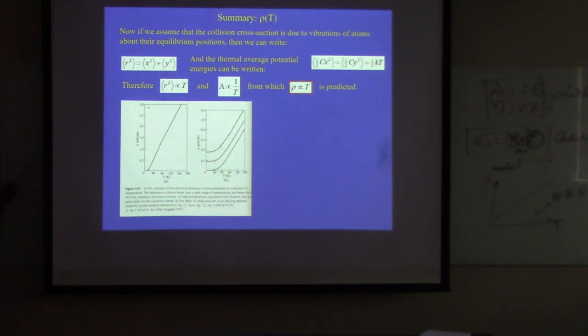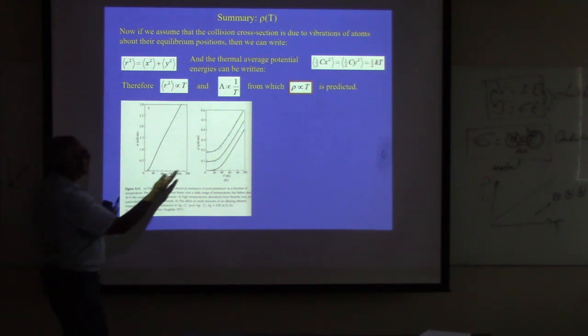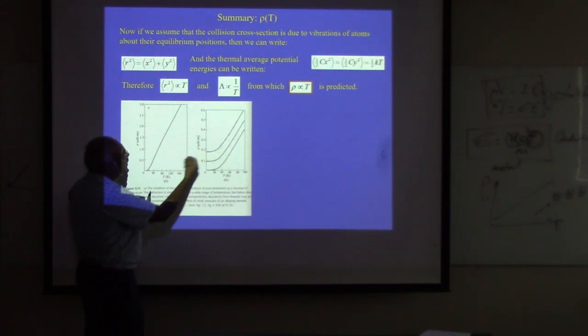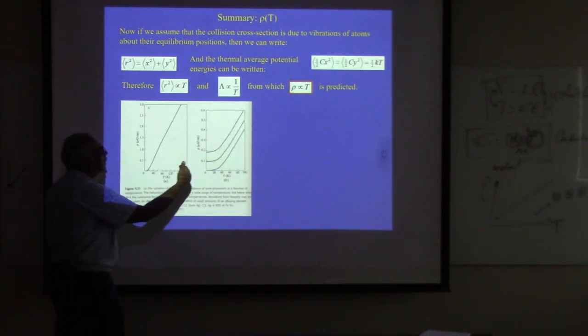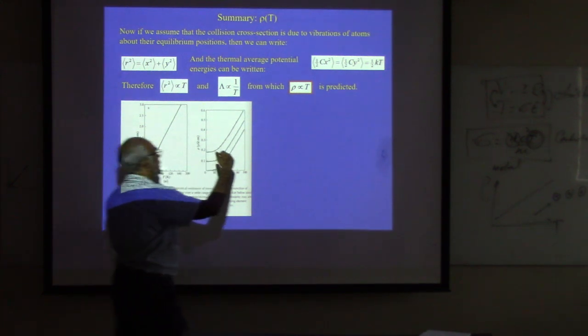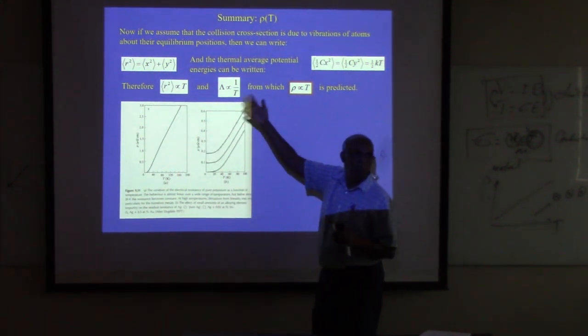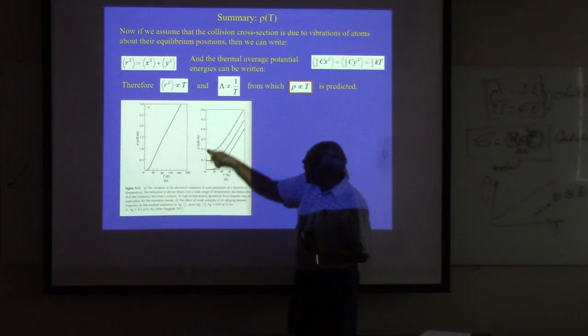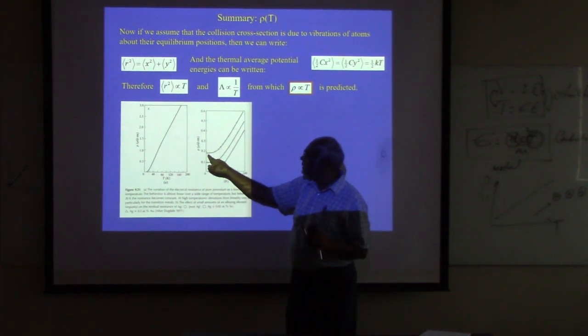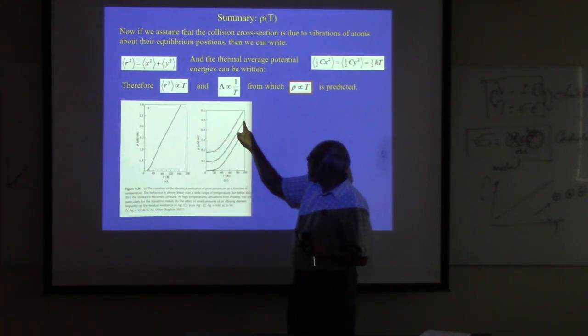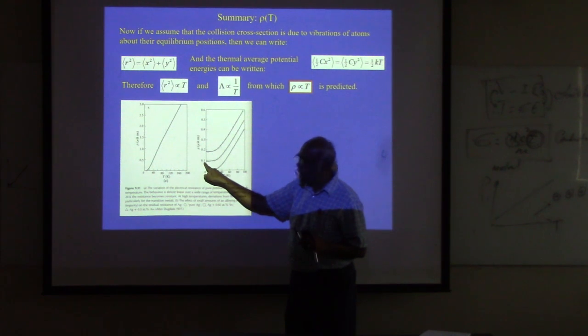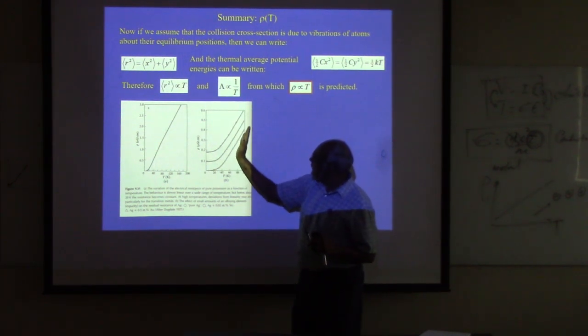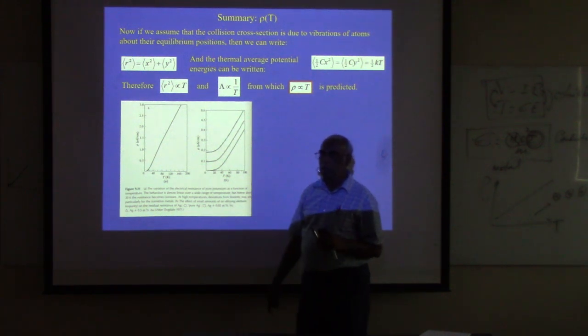Ideally at 0 Kelvin, you should have zero resistivity, right? But it always has some impurity, that's why it just saturates to that value, not 0. People have shown that by purposely adding impurities. When you add impurities, you can see your resistivity, even the initial resistivity, is increasing because you are putting in more impurities, right? So then it saturates at a higher level because that's the residual resistance, right? Here you can see these parts are linear but saturate at lower resistances.